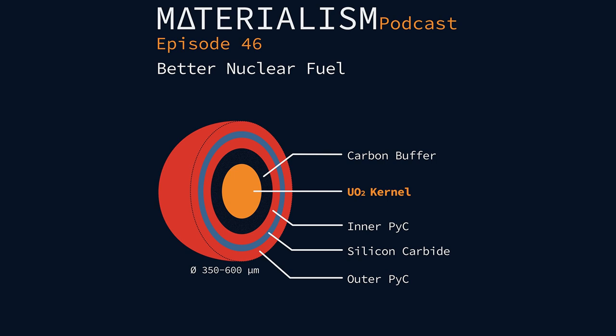So how do carbides or other materials fix this problem? Just they're less prone to react, and so you're not forming that carbon monoxide? Yeah, so this is what the U.S. then started pursuing. Germany largely tried to stick with the uranium oxides, and their solution to this kernel migration problem ended up just being more stringent manufacturing, as well as lower temperature gradients. So you're not going to be able to operate your reactor as hot, or you're going to have to design it in a way that you don't have as intensive gradients.